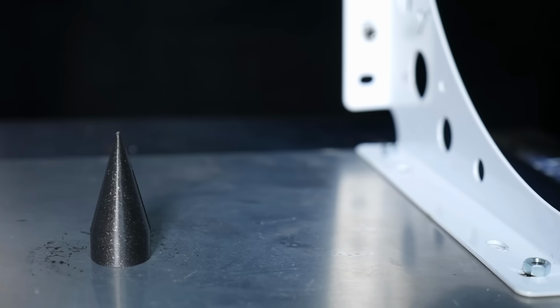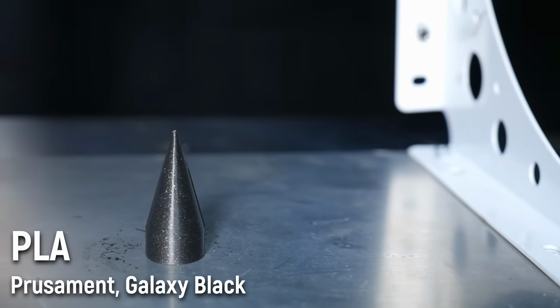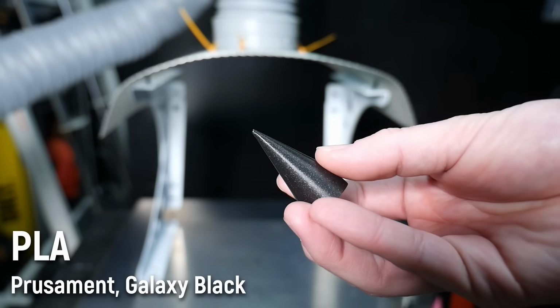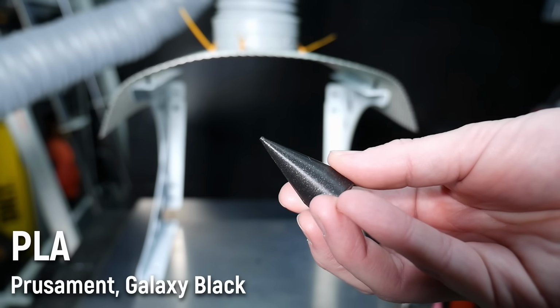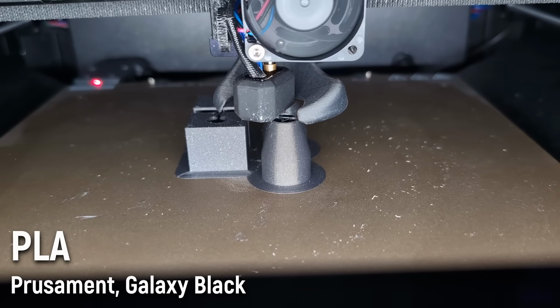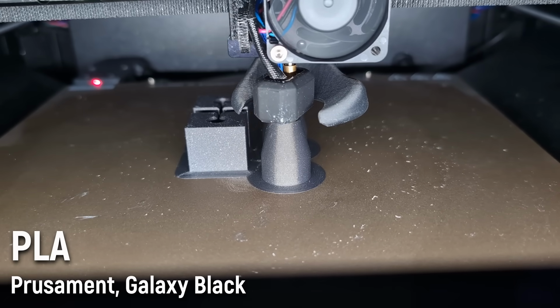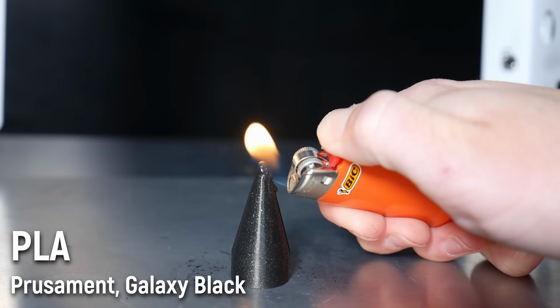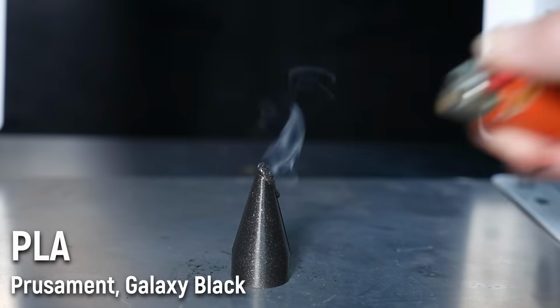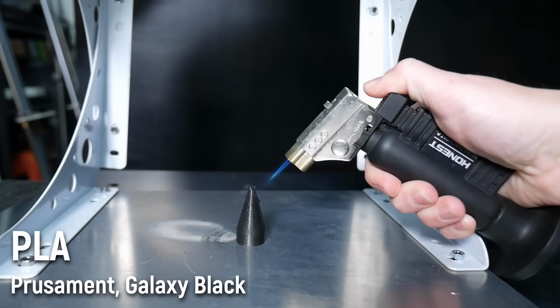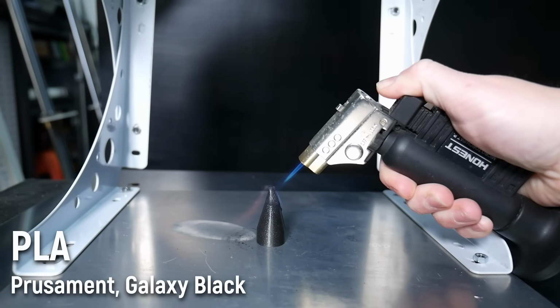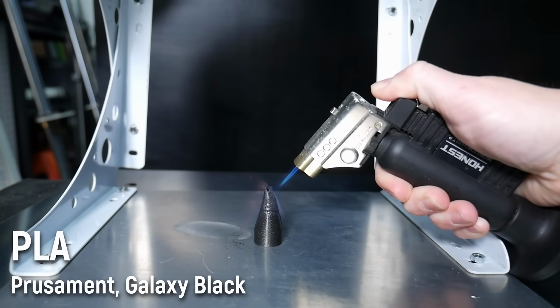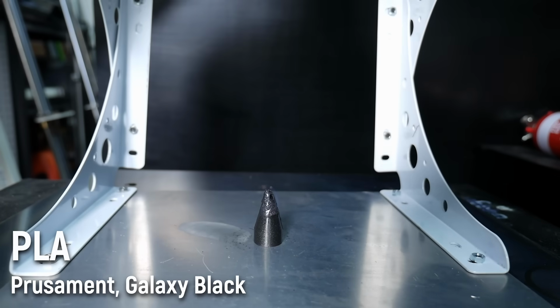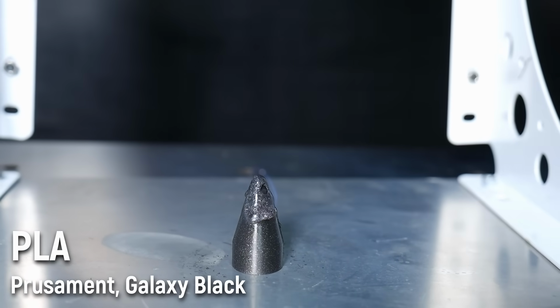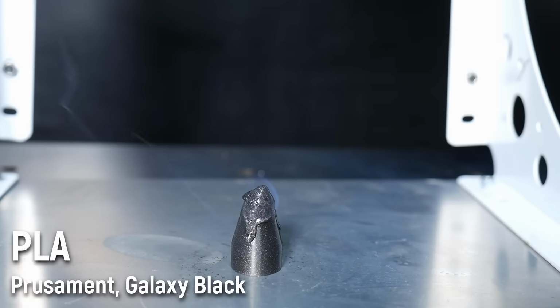That's good to know. The next PLA is Prusa's Prusament Galaxy Black. This is by far one of the prettiest PLAs on the market, and it prints really well too. It has a black translucent look with those little sparkles to help hide the pesky layer lines. And when subjected to the lighter for a few seconds, it would instantly self-extinguish. So I stepped it up to the blowtorch, and something really interesting happened. It looks like there's no flame, but if you look closer, it is actually burning. The blue flame is really hard to see, but it's definitely on fire and melting rather fast.